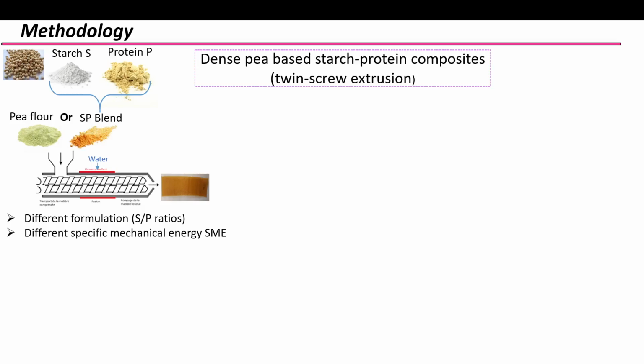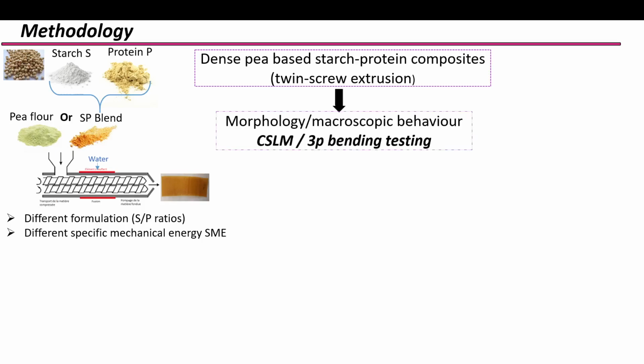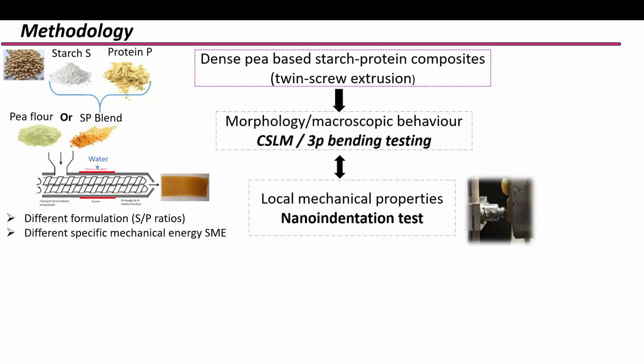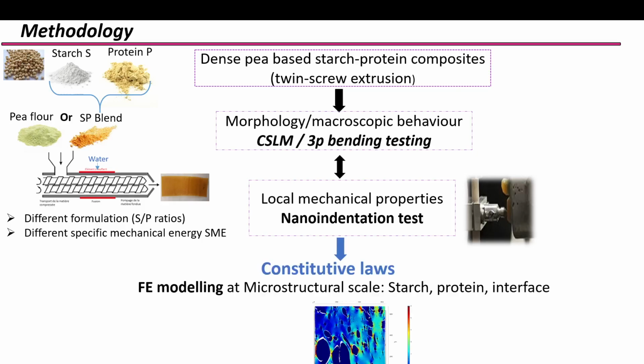So the idea was to design some pea-based starch protein composites using twin screw extrusion, using different formulations and different specific mechanical energies. We also did some morphology and macroscopic behavior determination using CLSM and 3-point bending testing, and also some local mechanical property determination using nano-indentation tests, and combined all these experimental data towards predicting the behavior of the pea protein composite material using finite element computation, both at the macroscopic and the microscopic scale.